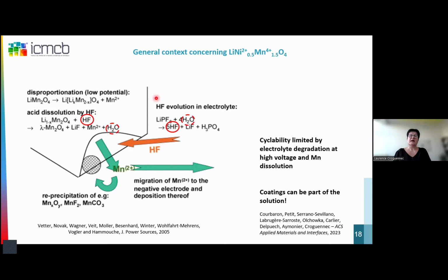Because you can see here that as soon as your electrolyte, your salt here, is degraded, we form some HF. And of course, here we can have an acid dissolution of our materials at the surface, and especially the solubility of manganese 2 plus generated by the dismutation between two manganese 3 plus, giving one manganese 2 plus and manganese 4 plus, and then migration of this one at the negative electrode, and being the source of loss of performance for these materials. So of course, we really want to mitigate the amount of manganese 3 plus in these materials. I just wanted also to mention that, of course, coating can be a part of the solutions also in order to stabilize these interfaces.